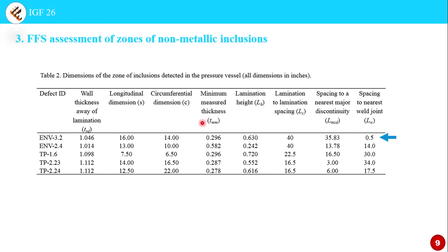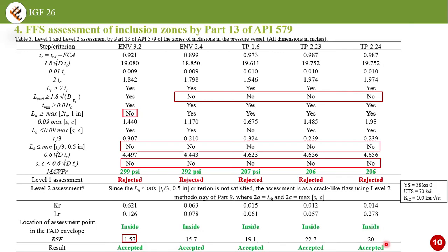This table shows the dimensions of inclusion zones and parameters cited in previous slides. Please remember this value for these non-metallic inclusion zones, because this zone is so near the weld metal, as I said in the previous slide, and LW is the important parameter that has an effect on the procedure of fitness for service assessment.